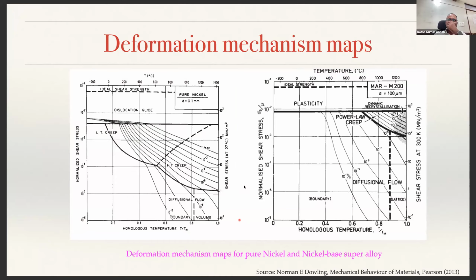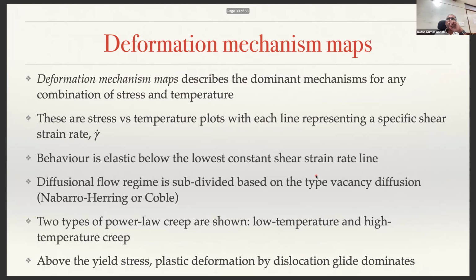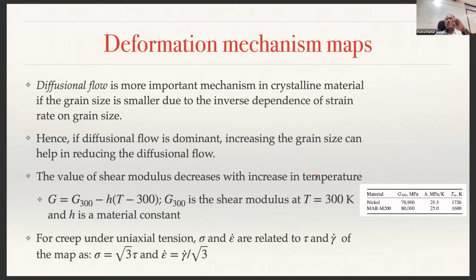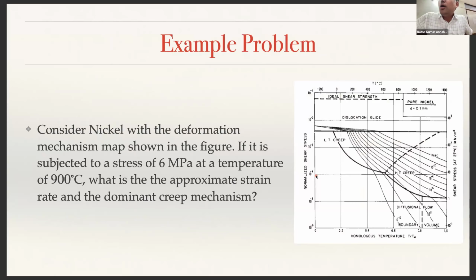Again, as I showed you earlier, you have pure plastic deformation if the homologous temperature is less than 0.4, only plasticity takes place. As your homologous temperature increases, then depending upon the stress value or strain rate that you are operating at, different mechanisms take place. This is the power law creep domain. This is diffusional flow, and there's nothing here. Okay. Yeah, this is the same mechanism.